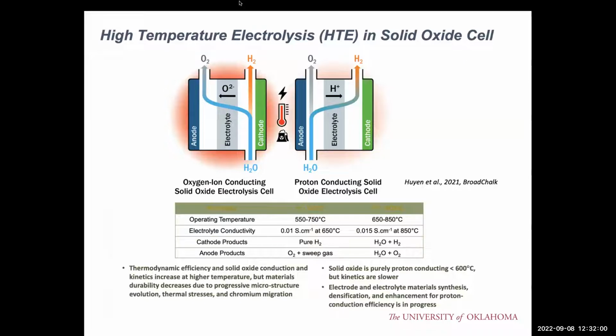One is the operating temperature. The conventional oxygen ion conducting SOC is operated at a higher temperature, like 650 to 850 degrees C. So it's pretty high temperature. This high temperature can increase the manufacturing cost of the system because we need to apply very expensive interconnect material. So the manufacturing of the interconnect material is very expensive. That can consequently increase the total cost. And also the high temperature can challenge the materials system, the interface and also the compatibility between each different material layer.